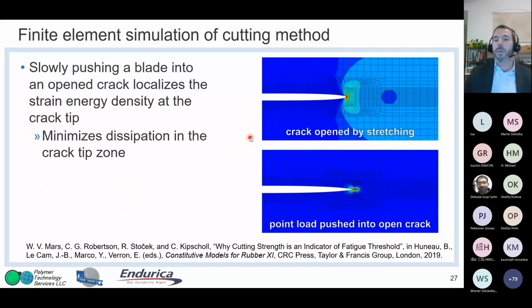This is just a 2D simulation. If you do a hyperelastic simulation in Abaqus and you put a crack, if you open up that crack, you can see these colored regions here showing that what you're doing is out in front of the crack as well as at the crack tip. And when you push a point load into that open crack, now everything shrinks down. It's a very localized strain energy density region. So that was a nice simulation that Dr. Will Mars did to show how the cutting method can minimize dissipation.